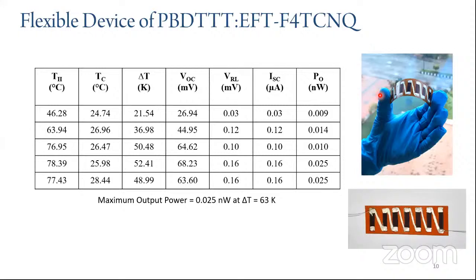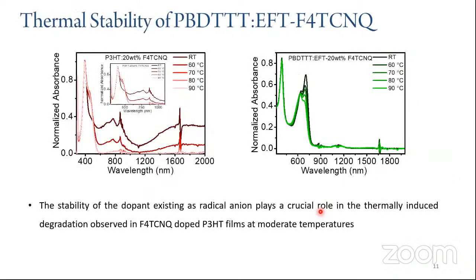And we have also fabricated a flexible device of the PBDTTT with 20 weight percentage of dopant using polyimide sheet, with the fabricated TEG showing an output power of 0.025 nanowatt at a delta T of 63 Kelvin between the hot side and the cold side, with a maximum output voltage of 0.16 millivolt and a load resistance of 1 kilo ohm. And coming to the F4TCNQ doped polymer blends, a major challenge faced is their de-doping.